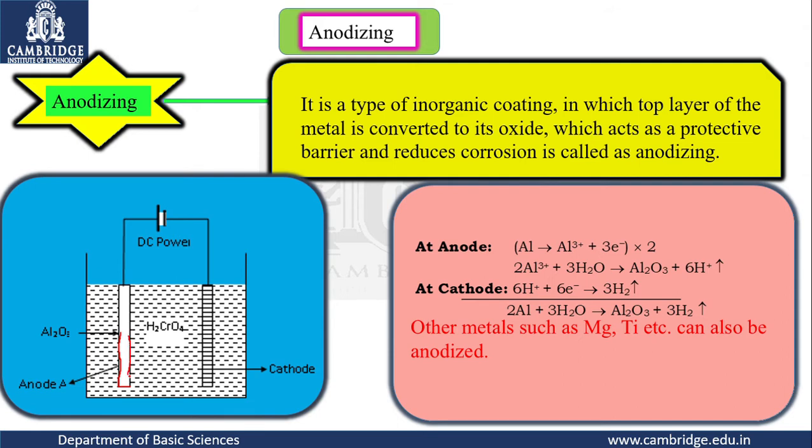See, the temperature is maintained at 35. Voltage is gradually increased from 0 to 50. At 50, it should be maintained for 10 minutes. At that time, the top layer of the metal, aluminium, oxidizes to Al3+ and releases 3 electrons. This is what is happening in that 10 minutes course. So once the connections are done, voltage is increased to 50 volt, and at 50 we have to maintain it for 10 minutes. At that time the top layer of the metal oxidizes to release the electrons.